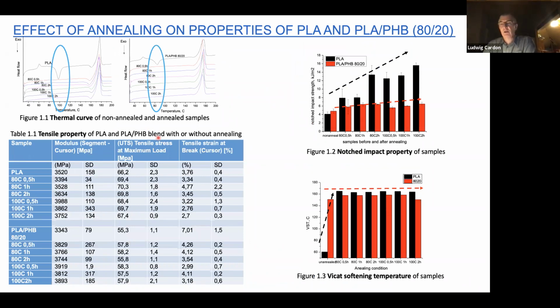We also investigate annealing. For PLA, for instance, you have the cold crystallization, but after annealing, we avoid this cold crystallization, and we also improve the recrystallization of the material, so that finally, as you can see in these two graphs, by annealing the unannealed black material of standard PLA, the Vicat softening temperature increases a lot. When we have blends, it does not increase, but depending on the impact behavior, the annealing also has an effect depending on the type of blend of PLA or PLA PHB. So this is a kind of investigation we also do to see if you need post-processing after your polymer processing or 3D printing.